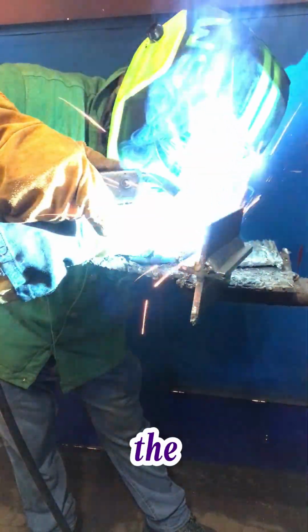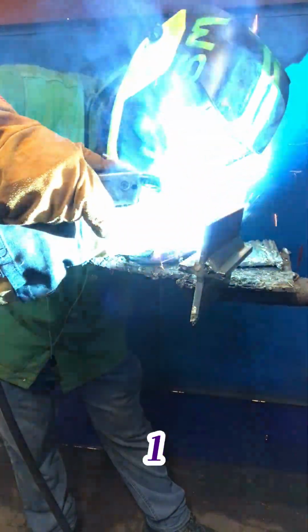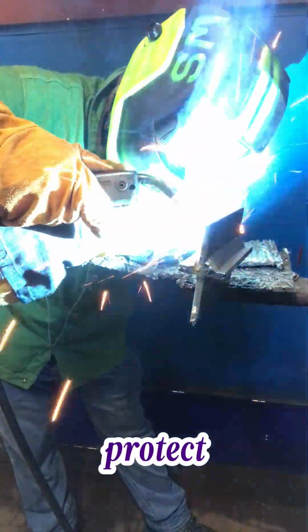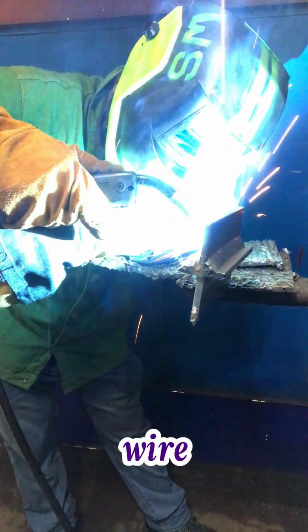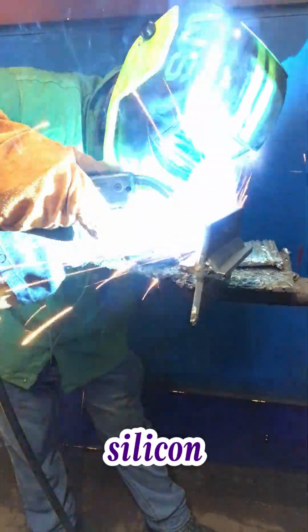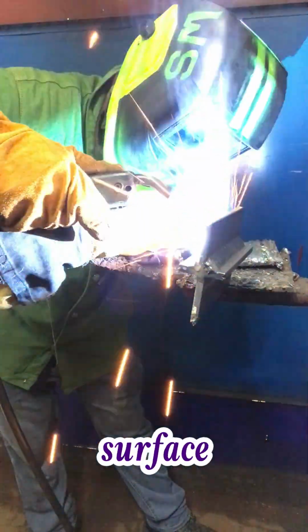Once you reach the end of the plate, hold the torch steady for 1 second to allow post-flow gas to protect the cooling crater. Use a wire brush to remove the thin glass-like silica islands on the bead surface.